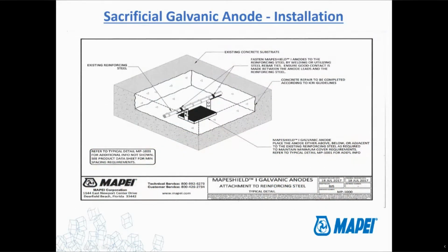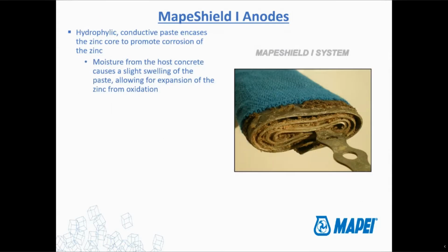But it's pretty typical. You'll attach them. They'll have two metal wires of some sort sticking out of them. Then you'll make sure you get good electrical contact with the reinforcement bar, and then strap it to the bar to make sure it stays in place. They should always be done around the edge of the repair because that's where the big potential difference is happening. So if it's a really big 10-foot by 10-foot patch, you don't really need them in the middle of that 10-foot by 10-foot square. You really just need it around the perimeter typically.